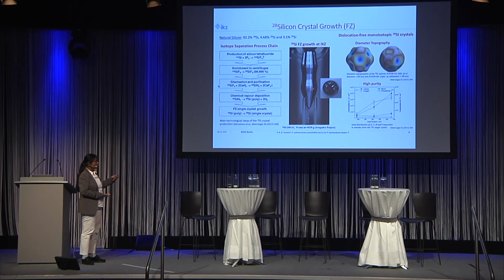But this isotopic material is enriched in Russia, so all these process steps should be done before getting the isotopic material, starting from silicon tetrafluoride and then doing the CVD to get the polycrystalline rod for growing the single crystal, and then the floating zone crystal. These floating zone crystals, we can purify chemically as well, up to very high purity. And you can see here that the concentration of impurities is in the order of 10 to the power 14 to 10 to the power 15 per cubic centimeter. Oxygen and carbon are the main impurities, and they are well under 10 to the power 15. This is very important for people who want to fabricate a device.